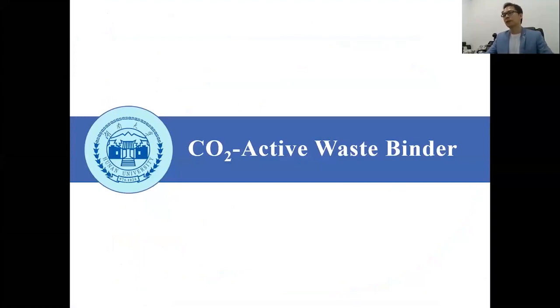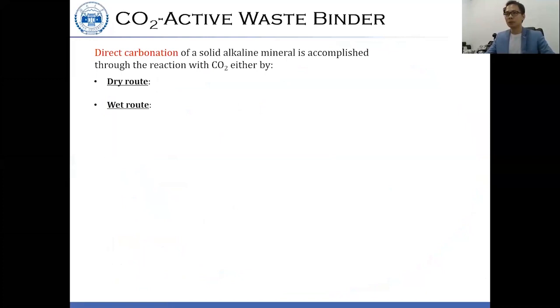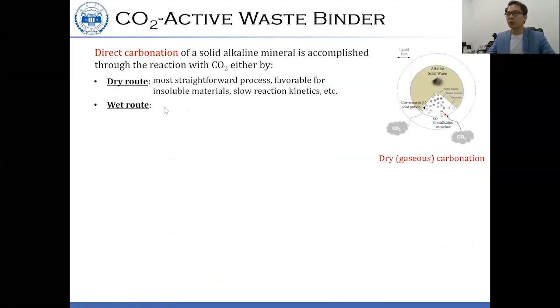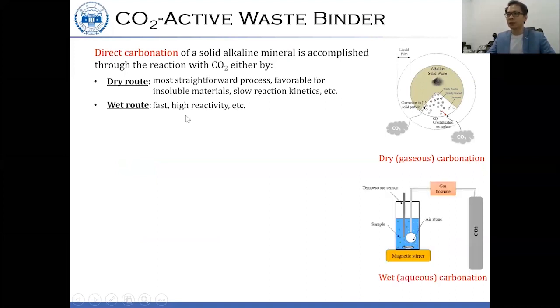First part, the CO2 active waste binder. In the construction industry, we usually adopt the direct carbonation approach because it is less complicated and does not involve any extraction or the use of chemical reagents. Direct carbonation can be accomplished through reaction with CO2, either by a dry route or a wet route. The dry route is more straightforward and favorable for insoluble material. However, the reaction is slightly slower. But for the wet route, the reactivity can be enhanced through ion mobilization in the reactions of carbonic acid with alkaline metals.